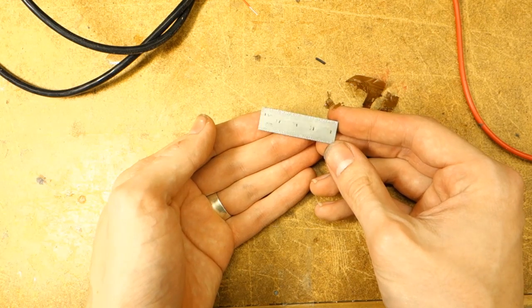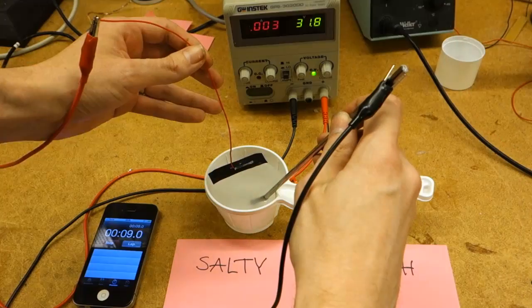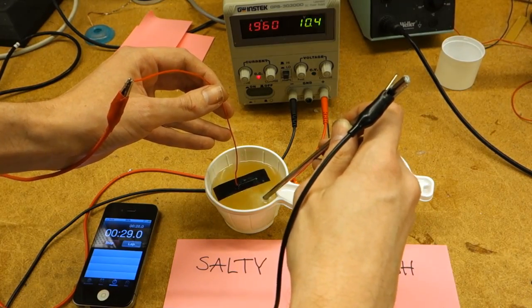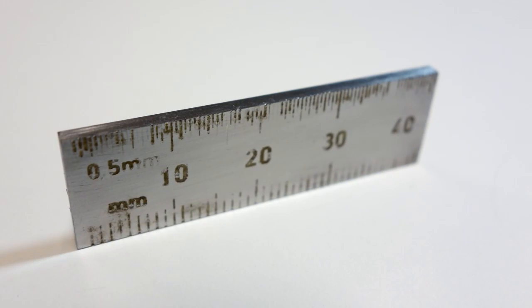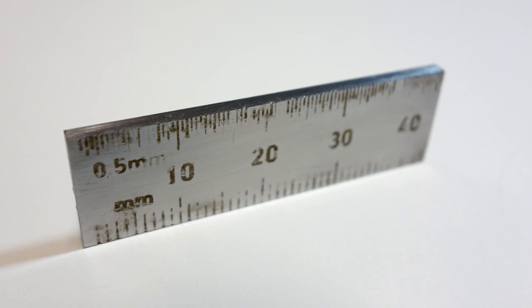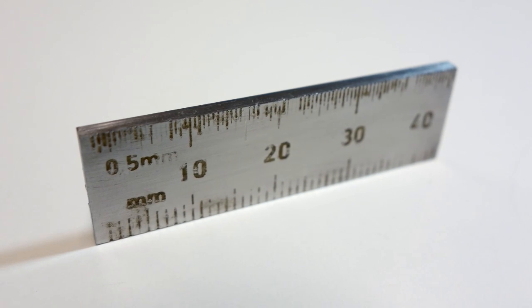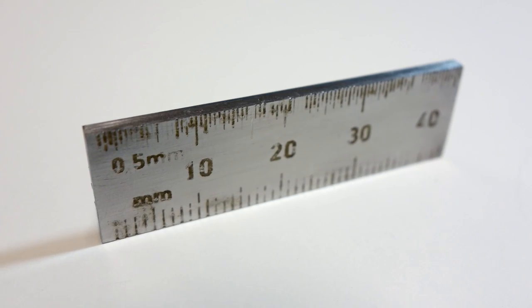Let's backtrack here and see what happened. The piece was put in flat on top of the surface of the water, creating small pockets of air which prevented the electricity to reach all parts of the pattern. This could easily have been prevented by simply rubbing the surface with a bit of water before dunking it into the cup.